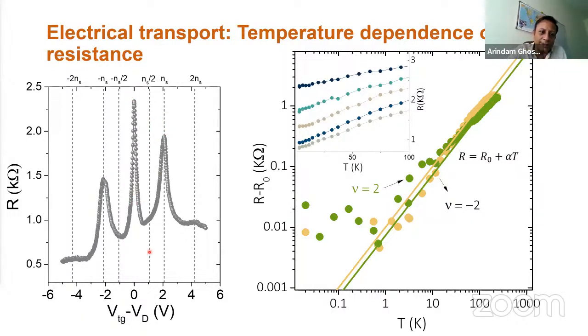And you can see one of the interesting aspects is that when I look at the half filling, which is at the center point between these 2 peaks and these 2 peaks, this is the half filling points, these center lines. If I measure the electrical resistance as a function of temperature at this half filling, we see a linear temperature dependence over nearly 2.5 orders of magnitude of temperature. So all the way from 0.3, 0.4 Kelvin to about 200 odd Kelvin, we see really nice linear temperature dependence, which is one of the controversial points, that whether the system is obeying the Fermi liquid theory or not. Okay. So these two are essentially plotted corresponding to this temperature, this gate voltage at half filling.